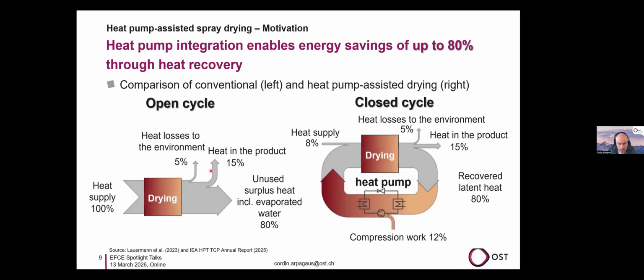Now, if we can close this cycle with a heat pump, so we use the exhaust humid air as a heat source and upgrade it with a heat pump to inlet air temperature again, we can close the loop, and so the heat supply can be reduced a lot. So theoretically, this could be 80% heat recovery in such a closed loop. This is valid for any drying processes, but especially also for spray drying processes.